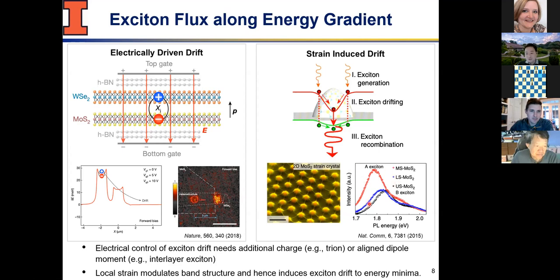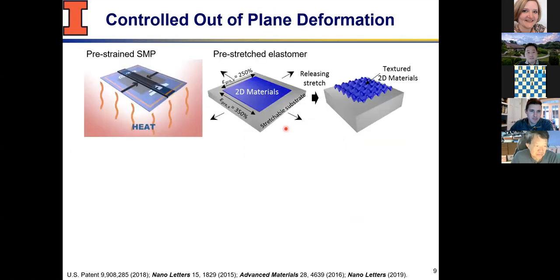They showed some evidence of that by looking at exciton intensity. More are condensed or drifted towards the tensile portion, not the other portion. So that's why you're seeing higher intensity. I'll talk a little more about that in my slides, probably the next slide. But these are the two major ways that people have been working with: either some fancy interlayer exciton coupled with electric field, or just strain. But now we can deal with the intralayer, so that's the one-layer material excitonic system.